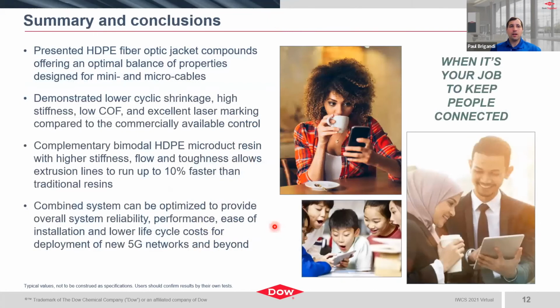So just in summary, we've looked at these high density jacket compounds that we can design for an optimal balance of properties, depending on what application areas you're working in, whether it be for mini and micro cables or other applications, be it data centers, et cetera. We've shown the ability to have lower cyclic shrinkage, higher stiffness, a lower COF, and excellent laser marking compared to traditional materials used in the field, as well as this complementary bimodal high-density polyethylene for the microducts to allow for higher stiffness and toughness.